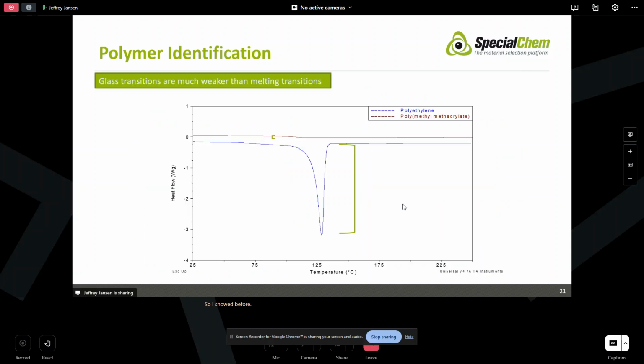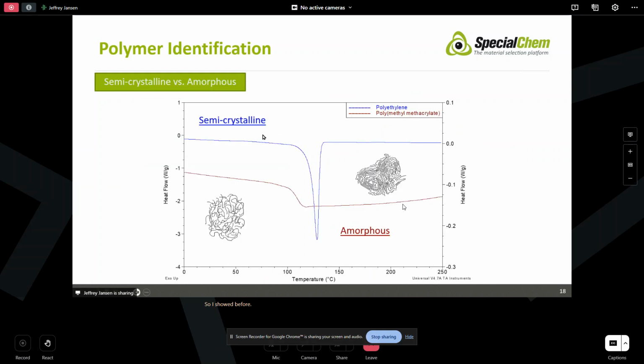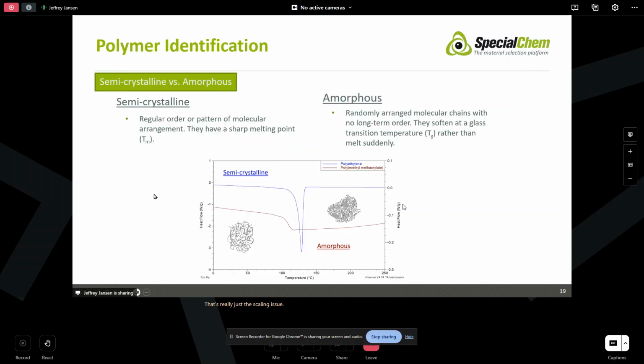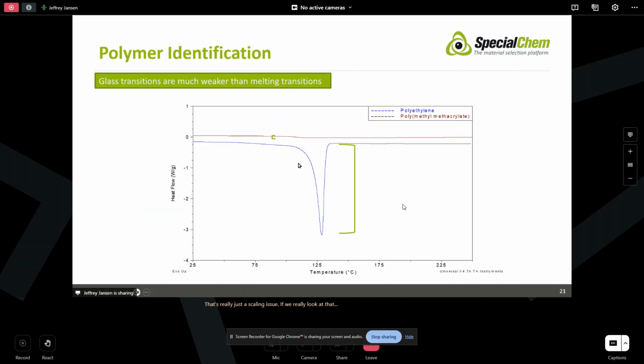Okay, so I showed before, let's look at that. I showed before kind of these two transitions, the glass transition and the melting endotherm, looking like they're on the same order of magnitude of intensity when it comes to heat flow. Well, that's really just a scaling issue. If we really look at that, they are not. A melting endotherm typically is much, much stronger. We get a much bigger change in heat flow than we do with a glass transition. The glass transition much, much weaker in terms of its response. So again, don't be fooled by what I showed you there. That glass transition is relatively weak, and that's going to play a role. We need to understand that when we're starting to think about contamination. More about that in a little bit.